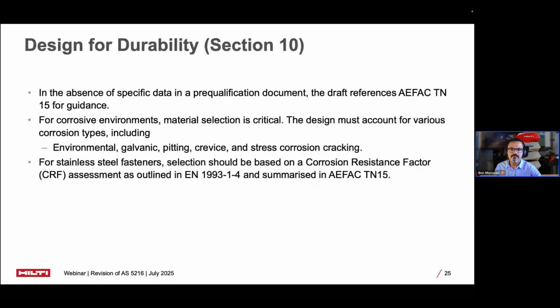Okay, so when specific durability data isn't available in a pre-qualification document like an ETA, the draft references AEFAC Technical Note 15 for guidance. This comprehensive document provides practical approaches for durability assessment. For stainless steel fasteners, selection is based on the corrosion resistance factor, which is the CRF assessment, as outlined in EN 1993-1-4. This systematic approach matches stainless steel grades to specific corrosive environments, ensuring appropriate material selection for the intended service life.